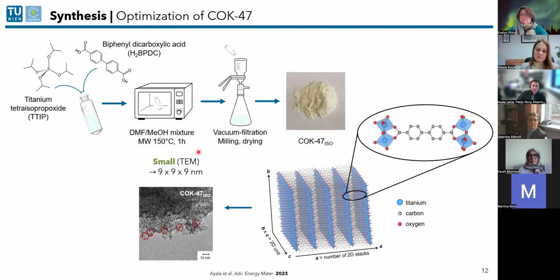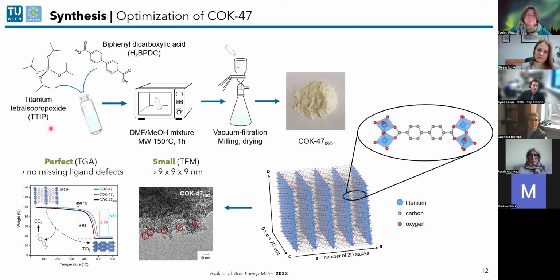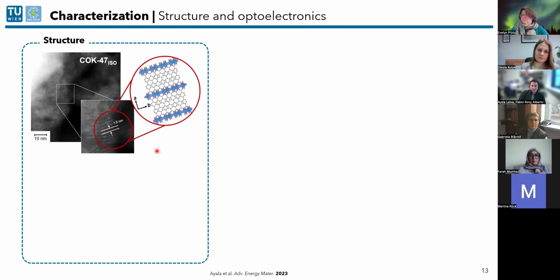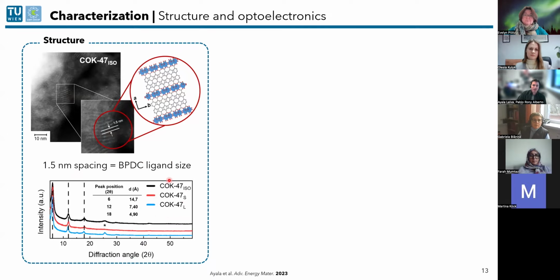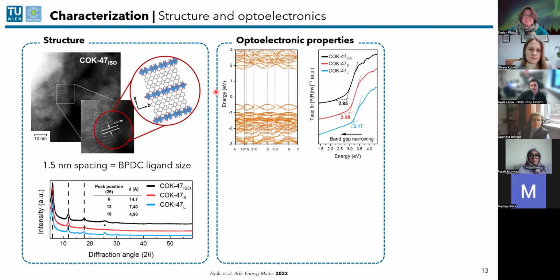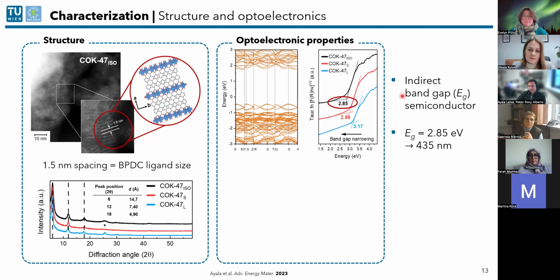So the size, the dimensions, we estimated with TEM, and then the perfectness, so here we mean by that no missing linker defects, we estimated through thermogravimetric analysis. Okay, and so some further characterization that I really like about this first publication was these high-resolution images where we see this lighter lamella of the titanium oxo sheets, which are separated by 1.5 nanometers, which is exactly the size of the ligand. Then, of course, we did powder XRD. All particles gave the same diffractogram, but we are maybe a bit more interested in the optoelectronic properties. So with theory and also experiment, we assessed the band gap.